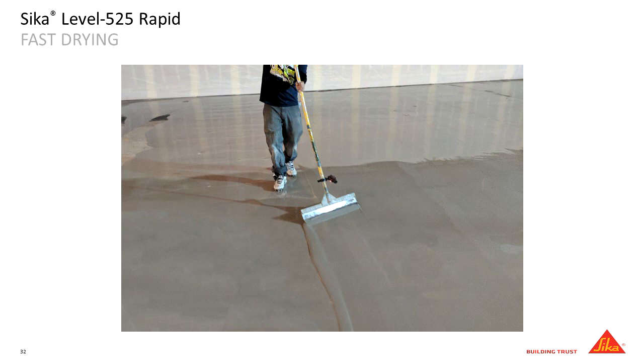time from taking a concrete slab that's recently demoed, high moisture, and out of level. In 5 hours, you can get that moisture under control and a flat surface to install any floor covering. There's really no system out there that can do that quickly and take care of all of those headaches, moisture and the levelness pitting of the substrate, to make sure that you're ready to come back and install a soft type of product that will telegraph.